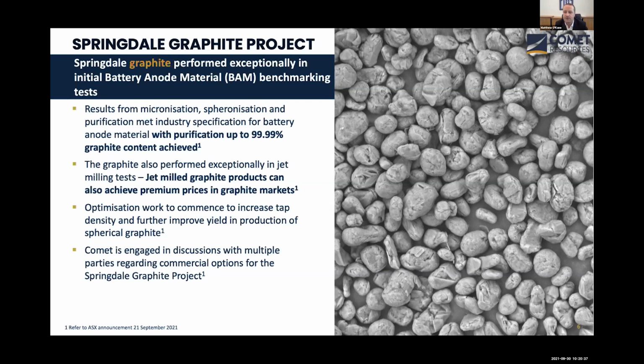We sent that over to a specialist testing facility in Germany, Pro Graphite, where they tested the material for the three key processes in manufacture of battery anode precursor material, which is first of all to micronize the product, because you start out with very small flakes for spheronization. So you have to micronize down to around about 15 microns or 20 microns. They're the two starting sizes for input into spheronization.